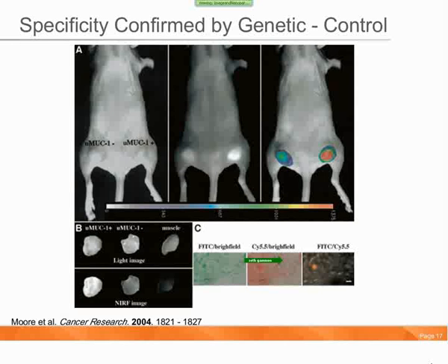When the nanoparticle is taken up by a tumor, it actually causes a dark spot to appear. So they took a pre-contrast and a post-contrast image, and you can quite readily see, particularly in this view, that in the MUC1 positive cells you got significant darkening of the tumor compared to the MUC1 minus cells.